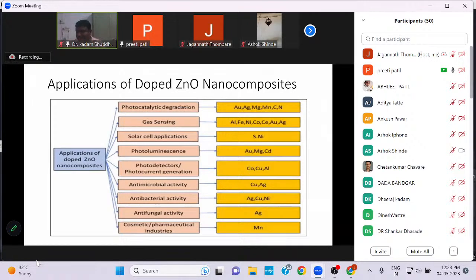Actually, if you go through the various research papers, I have referred to many of them. I have seen that non-metal doping like carbon and nitrogen also enhances the photocatalytic activity. Carbon doping, 30% carbon doped samples, show thrice the absorption compared to undoped ZnO. Similarly, nitrogen doping effectively reduces the band gap from 3.06 electron volt to 2.87 electron volt, and it is found beneficial in increasing the photocatalytic activity by almost 8-fold.